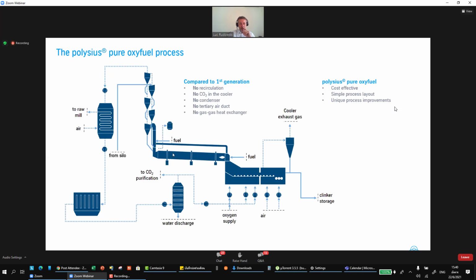So for that, you need a heat exchanger in order to recover the heat that you need for drying your raw material in the raw mill. You need to dedust that, and as well, you need to discharge the water before recirculating, and as well before sending to CO2 purification. Well, what we developed, in fact, is the pure oxy-fuel, and you will see that the separation in the cooler here between the first part where we are blowing CO2 and oxygen and the second part where you are blowing air, this separation is moved in the first part of the cooler here. Why? Because we are not recirculating any more CO2 here.